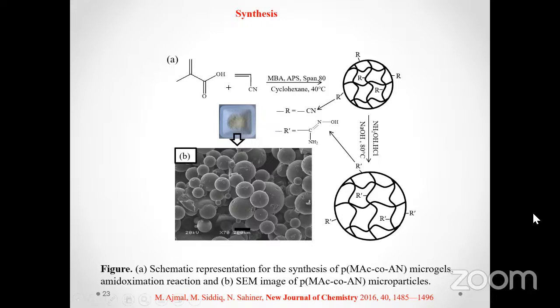So this was our target, and the amido oximes cannot be directly attached to the polymeric network. So first of all, we co-polymerized the methacrylic acid with the acrylonitrile. And then these nitrile groups were converted into the amido oxime groups. And again, we found that microgel particles were formed, and most of the particles had a particle size